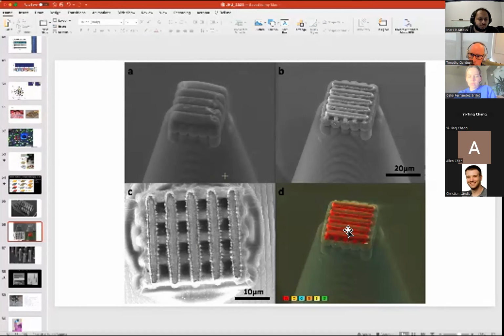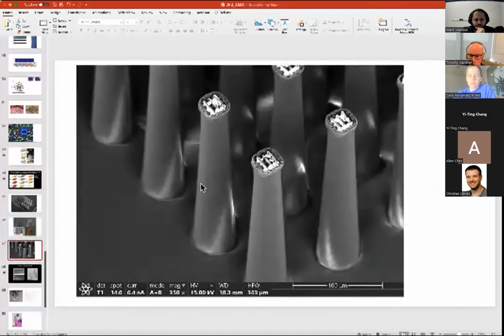So we haven't tested this systematically, but our concern was that if we just had essentially a flat surface when we did that laser cutoff, it would be too easy to completely remove all the metal from the top of the surface to create that recording tip. So we added this little structure, because with 2-photon lithography you can get really fancy with any structure you want to add to an electrode. And that so far looks like it's been useful. So here you can see in another image, these were the first prototype electrodes we built with that parylene outer coating and then the exposed platinum after the laser ablation.